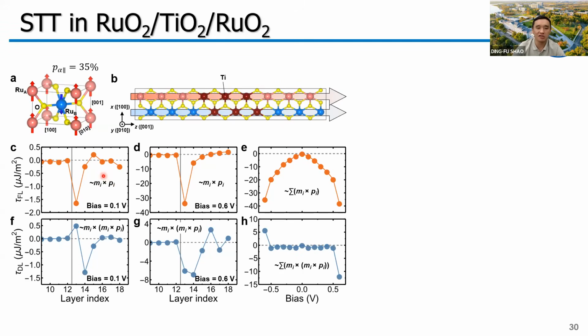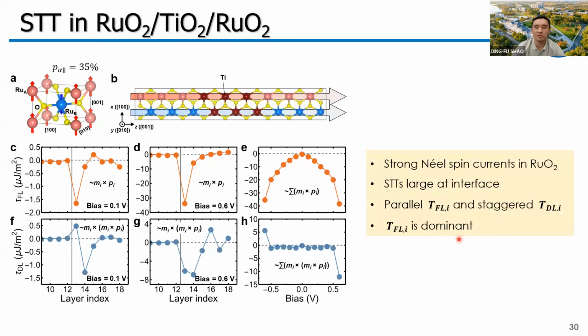which is consistent with the case for a conventional ferromagnetic tunnel junction, indicating the tunneling spin currents are mainly absorbed by the interfacial atoms. And we found that for the two interfacial layers, the field-like torques are parallel to each other, and the damping-like torques are antiparallel. This proves that the tunneling of the Néel spin current indeed transfers a staggered spin polarization to the right electrode. And we found that even if we have some uncompensated magnetic moment at the interface, which may generate additional spin current and enhance the damping-like torque if the bias voltage is large, the total field-like torque is always dominant, which can be used to generate the deterministic switching.